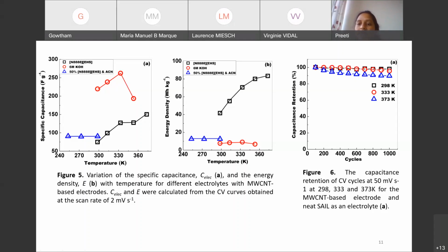And that's the reason that this ionic liquid is getting more and more interest as an electrolyte for supercapacitor devices. We have also checked the capacitance retention of CV cycles at different temperatures, 298, 333 and 373 Kelvin, and we can see that the retention is more than 90% even at the very high temperature of 373 Kelvin.